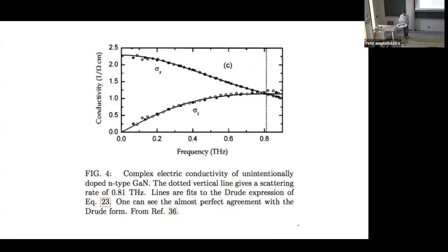There's optical conductivity, just to give you a simple case. The response functions are complex quantities. That's the real part, sigma 1, and that's the imaginary part, sigma 2. The dashed line is just the Lorentzian. The half width of this is literally, as I said before, just the rate at which current dissipates. That's its definition, there's no debate about what that means. It just comes from definitions. And then there's an imaginary part, which is Kramers-Kronig consistent with the real part.